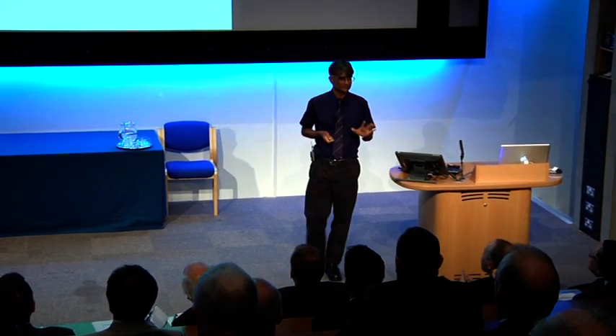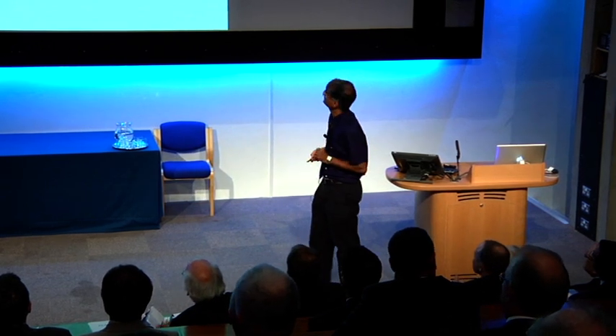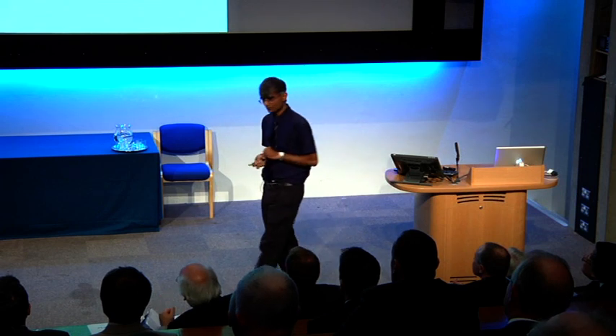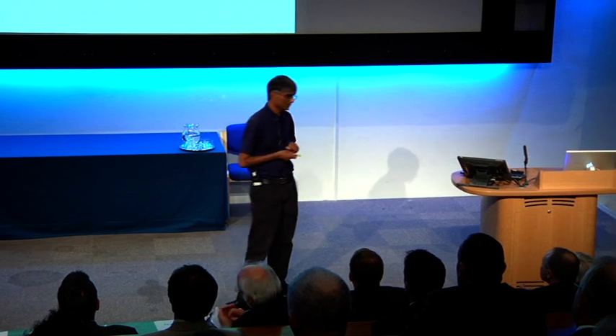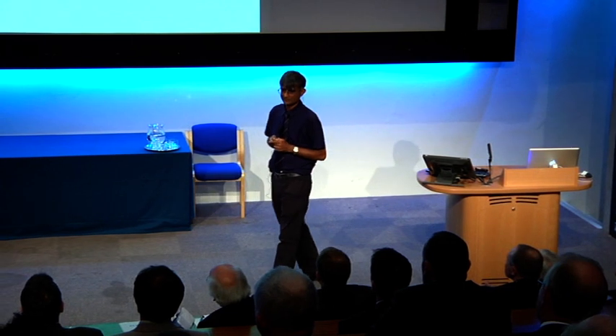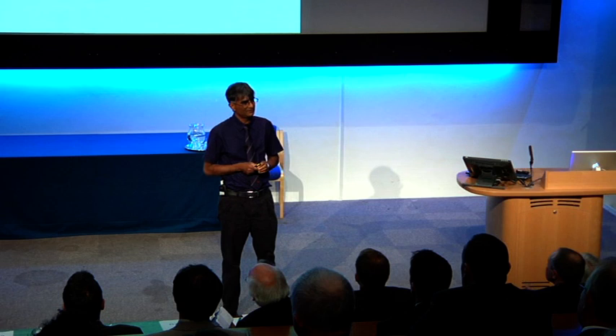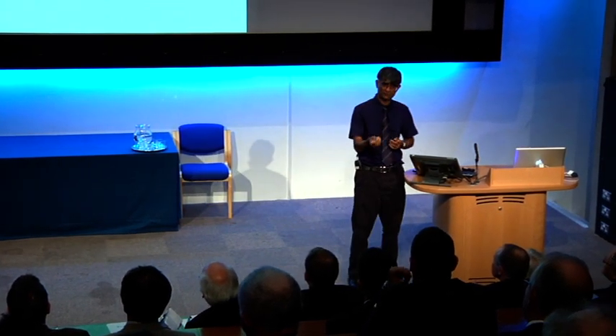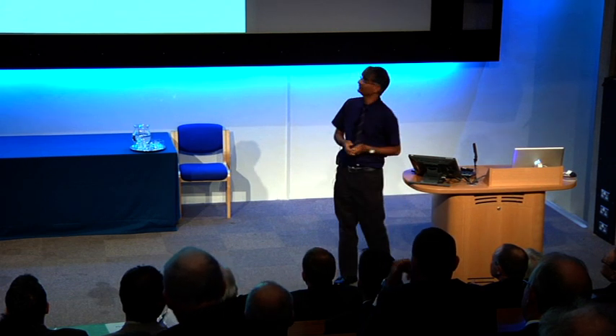So I've rounded off these numbers, and not all bearings work under these conditions, but there are certainly bearings that work in this way. So let's assume that we have a contact pressure of 2 gigapascals. We've got a ball on the surface, and under the surface we'll get a pressure of about 2 gigapascals. And it's going round at 25,000 RPM, revolutions per minute. And let's assume there are 20 balls in the ring. Then you experience a stress pulse at a point under the surface 500,000 times per minute.